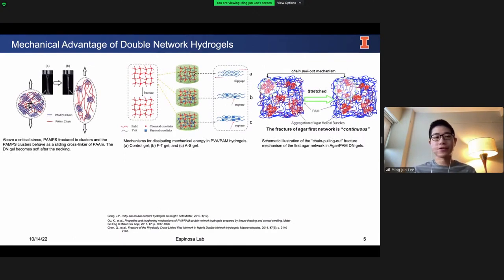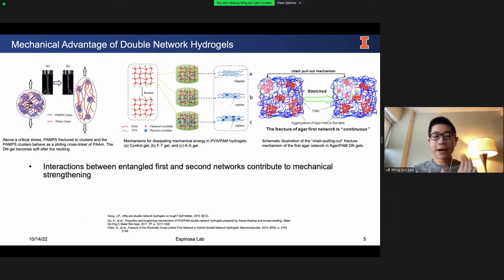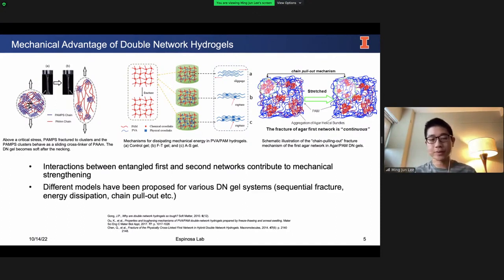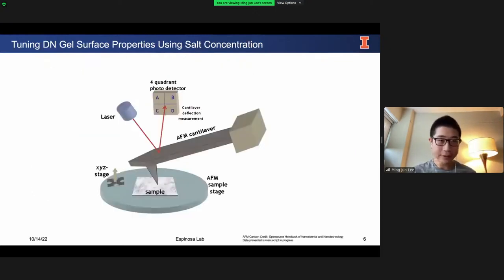And double network hydrogels can address one of the problems I mentioned earlier, where hydrogels need to be strong enough to sustain our body weight. Here I'm showing three different diagrams from three different papers explaining the mechanisms of energy dissipation in the double network hydrogel microstructure. What I want to highlight is that all these mechanisms have one thing in common, and that is the entanglement between the first and second networks. If we imagine a fishing net, where the horizontal strings are the first network and the vertical strings are the second network, this kind of entanglement between the two networks naturally leads to an enhancement in mechanical properties. Different models have been proposed, but they all have this one thing in common. And that's why I think double network hydrogels are suitable for synthetic replacements, at least in the mechanical space. Next, I would like to start talking about surface characterization, the adhesion and friction properties.